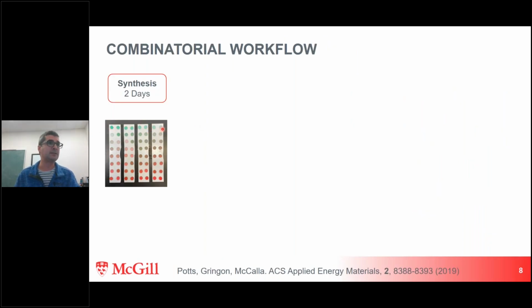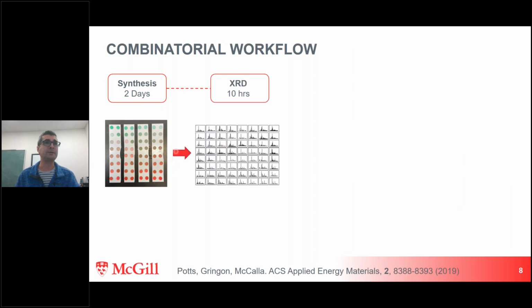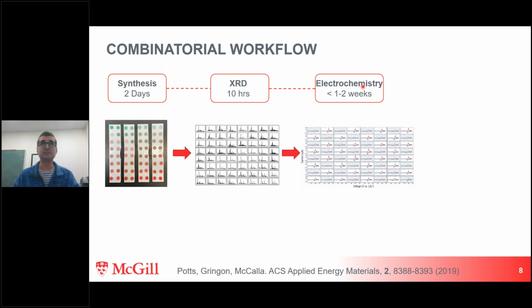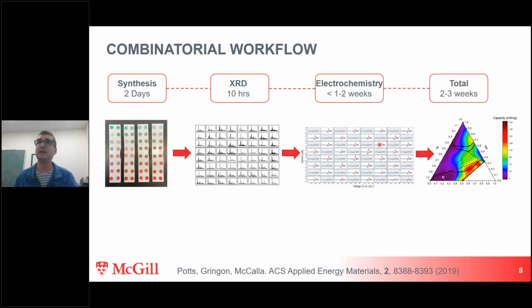We end up making these 64 samples on a plate. We get 64 XRDs in 10 hours. So we can run two of these plates a day. The electrochemistry takes about 1 to 2 weeks, and we have 10 of these channels. So we can run 640 samples at once. And then in 2 to 3 weeks, we can have this phase diagram, basically. So 64 samples can map out a ternary diagram. I'll show some of these for sodium-ion batteries.